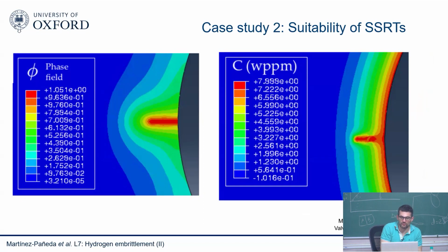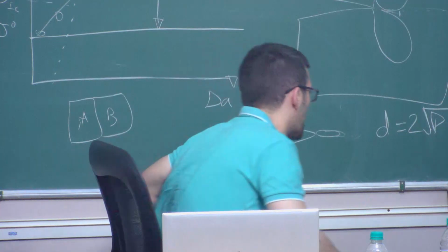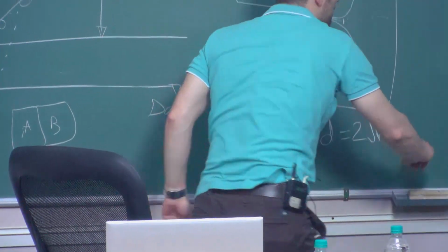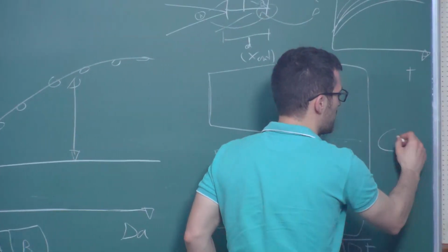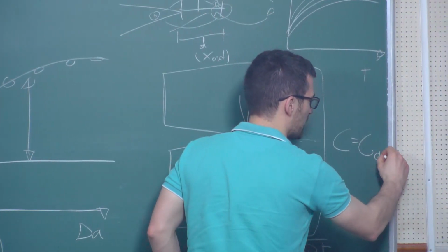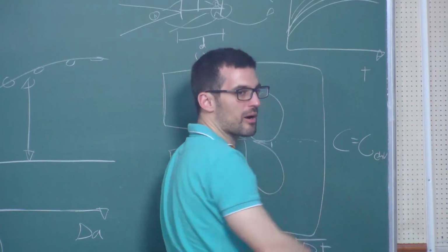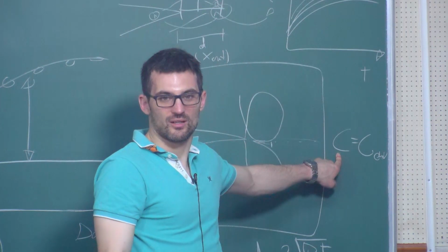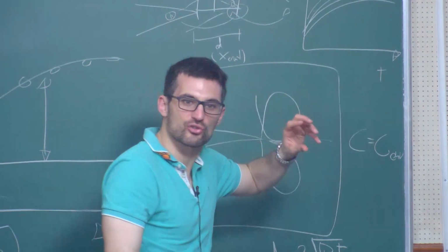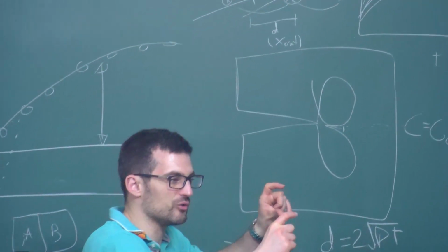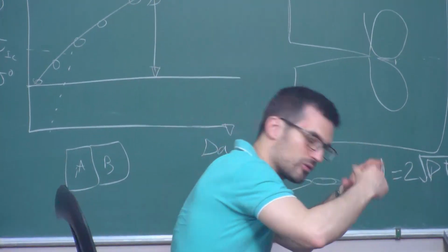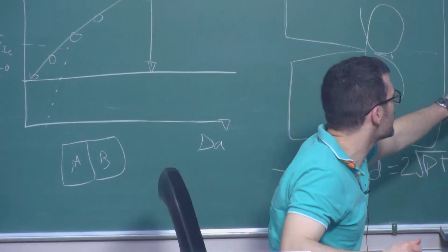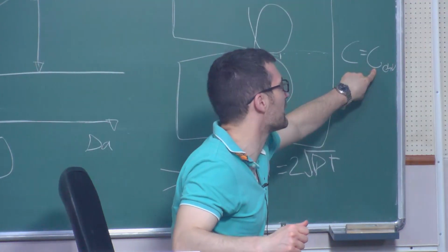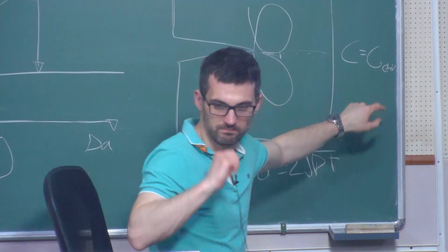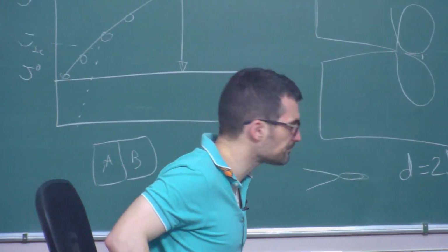And we have two ways of enforcing this. One is through a penalty approach. So whenever you're solving for your hydrogen concentration, basically what you want to do is make sure that in certain regions, let's assume that you have a hydrogen concentration from the environment, you are solving for C. So you have a penalty approach. You have a very large term where, depending on the phase field, you change the solution or your stiffness matrix and residual so that eventually the solution becomes this. This is one possibility. This is actually what we did in this paper.